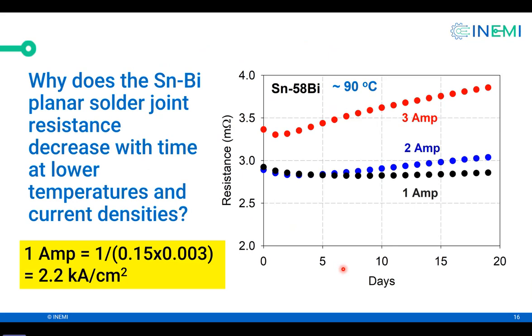Okay, so let's do a first experiment. So early on, when we started doing electromigration experiments, we saw, lo and behold, the resistance decreases. So you would think electromigration would increase resistance because of bismuth segregation at the anode, but we saw a decrease. So notice at 3 ampere, the decrease was for, let's say, 2 days. At 2 amperes, it was for about 5 days. And at 1 ampere, it was probably 7-8 days.